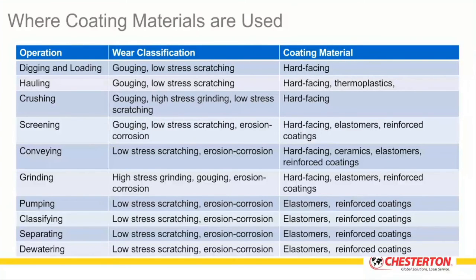So in that area, the use of hard facing, which could be metal-based welding, or thermal spray systems could be used. You can use the whole range of elastomers, which could go from rubber sheet to polyurethane and polyurea, and you can incorporate reinforced coating systems. It'll come down to cost, degree of difficulty, impact to performance. All of these factors will come into play as well, but from a pure materials performance characteristics, any one of those three systems would be advisable and suggested.